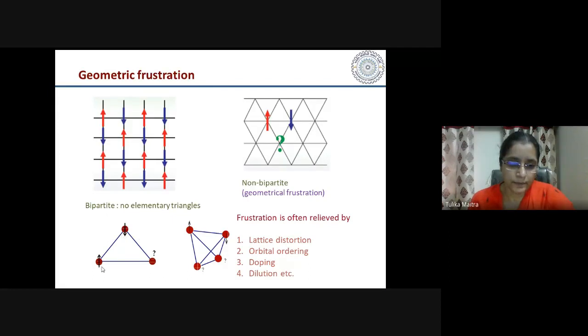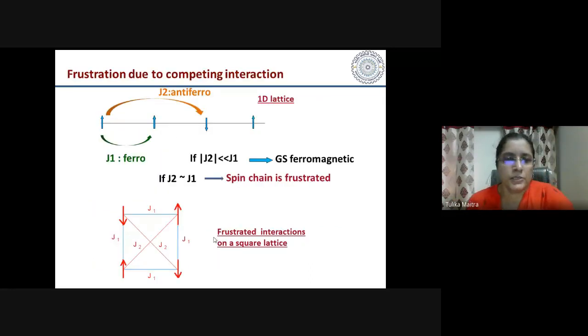So this is the triangle I was explaining, and this is the tetrahedron, which is the 3D counterpart of this triangle, which is also geometrically frustrated. And if you have a system where there is no geometric frustration, one can have frustration also due to competing interactions. Suppose we consider a one-dimensional lattice, where the nearest neighbor interaction is ferromagnetic and the next nearest neighbor interaction is antiferromagnetic, and they are comparable with each other, J1 and J2. Then the spin chain will be frustrated. You can also have frustration on a square lattice. For example, if your J1 and J2 are competing with each other, then one can have frustrated interactions. So here the frustration is not due to the geometry of the lattice, but due to interactions.